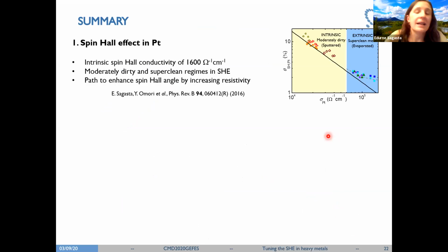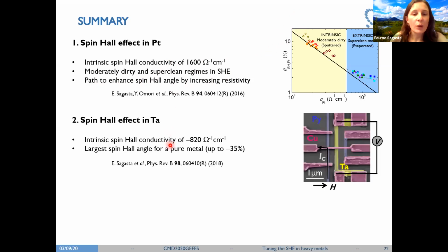So with this, I would like to summarize the talk. So first of all, we analyzed the spin Hall effect in platinum. We saw for the first time the crossover from the moderately dirty regime, where the intrinsic mechanism is dominating the spin Hall effect in platinum, to the super clean metal regime, where the skew scattering starts to take relevant part in the spin Hall effect of platinum. We have been able to extract the intrinsic spin Hall conductivity value experimentally, and also we are showing a path to enhance the spin Hall angle, which is to increase the resistivity of the material. In case of tantalum, we have been able to extract again experimentally the intrinsic spin Hall conductivity value, and to report the largest spin Hall angle value for a pure metal, which is minus 35%.